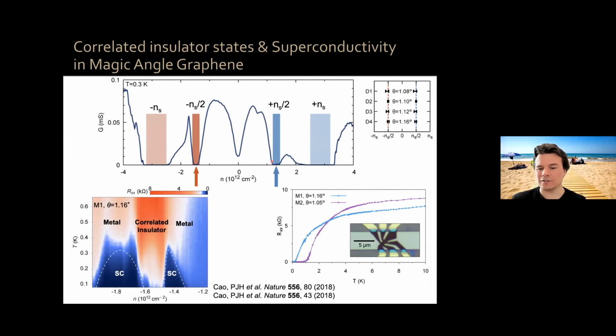Now, what we discovered, my group, back in 2018, is that if you put the chemical potential, the Fermi energy of your system in these flat bands, you have interesting correlated insulating states when you fill a certain number of electrons per moiré unit cell, and when you dope away from that filling factor, then you have superconductivity. This type of behavior occurs only in a relatively narrow angular range around this magic angle, let's say 1.1 plus or minus 0.1 or 0.2 degrees. So it's intimately connected to the presence of those flat bands for magic angle graphene.